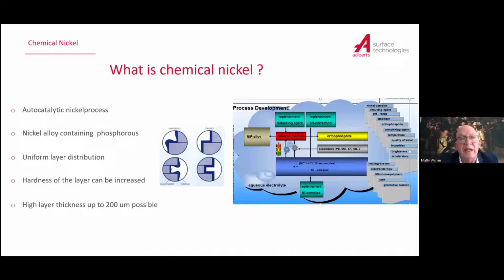And you put a part in that bath, a part which has a lower potential than the nickel itself. What happens then when you put the part in? The part acts as a catalyst. It starts a reaction in which the reducing agent falls apart. During that, it gives away electrons, and these electrons go to the nickel ions, which are in the solution, and they form nickel as a metal. During that process of breaking down the sodium hypophosphite, phosphorus comes free, and this phosphorus is also built up in the layer. And what you so get is a nickel alloy which contains phosphorus.